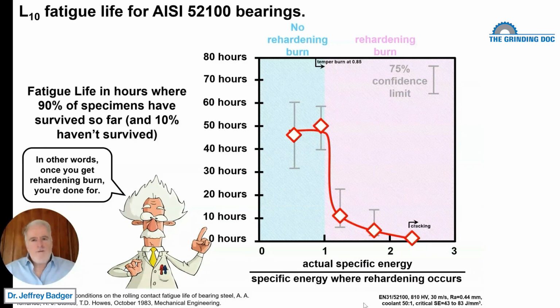Rehardening burn, white layer, phase transformation of the steel. The steel gets above the austenitizing temperature, recrystallizes, and turns into untempered martensite, a hard, brittle material. As soon as he crossed that austenitizing temperature and got the recrystallization, all of a sudden his fatigue life went from 50 hours down to 10 hours.